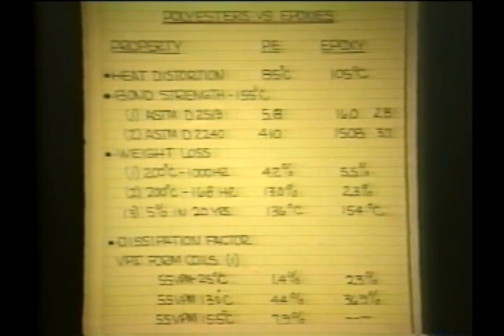And here again we find some differences but also some similarities. Source number 1 ran a test at 200 degrees centigrade for 1,000 hours, and the weight loss was 4.2% for the polyester versus 5.5% for the epoxy. Source number 2, 200 degrees C at 168 hours, 13% for the polyester versus 2.3% for the epoxy. And another test, not done on the same basis, but rather asking at what temperature it would take to lose 5% of its weight in 20 years. In this case, we have 136 degrees centigrade for the polyester and 154 for the epoxy, and there's not that much difference in that case.